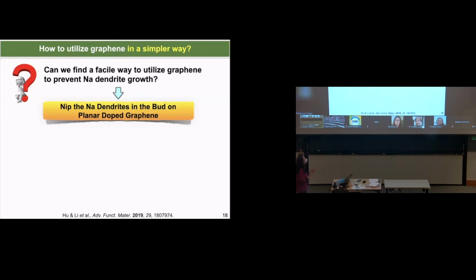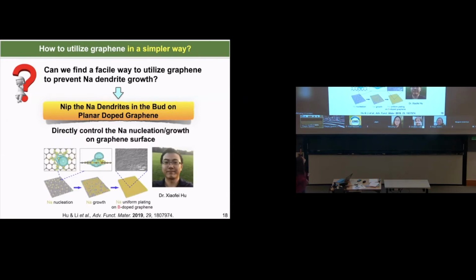In order to directly coat graphene on the surface of sodium metal, we began to think about how we can control the sodium metal nucleation and growth process, to directly control the sodium metal to be deposited onto a very thin graphene film. So we call it a planar doped graphene, to control the surface functionality of the graphene to directly realize a very smooth sodium deposition process. This work was conducted by my prior postdoc, Dr. Hu, who is now a professor at a university in China.